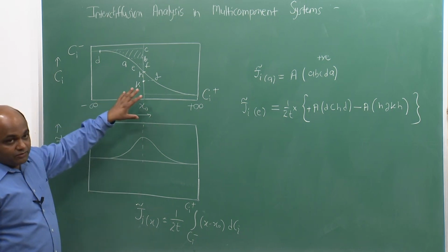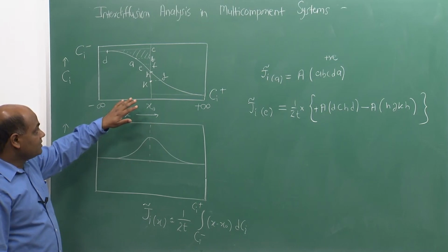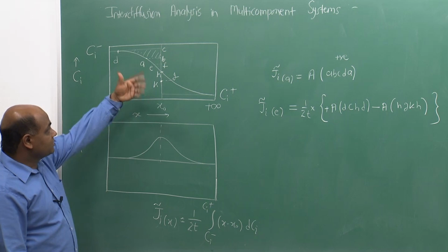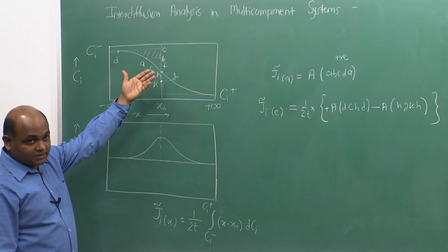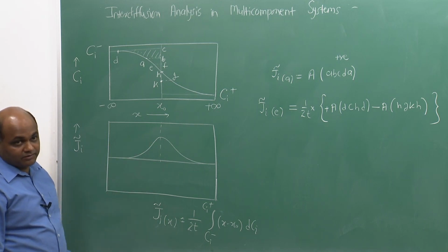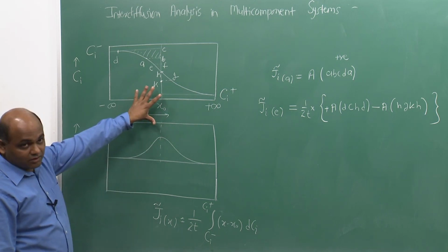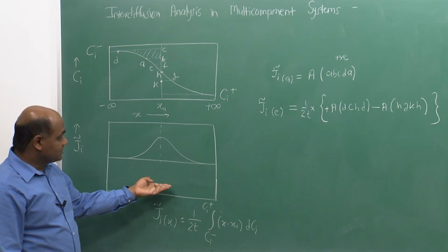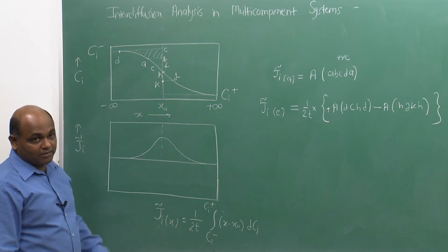Similarly, if we are dealing with a concentration profile which has the opposite gradient, a positive gradient, logically the interdiffusion flux will be negative. With similar logic, we can show there will be a minimum in the interdiffusion flux at the Matano plane location.